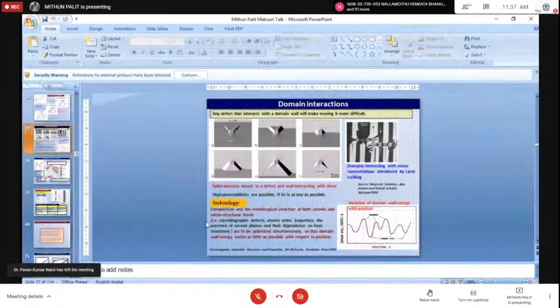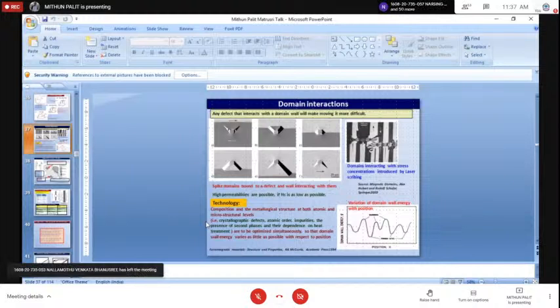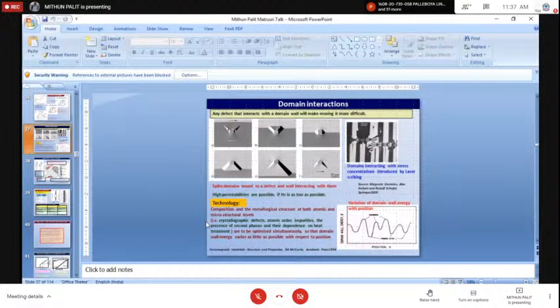So pinning means, for people who are from the material science background, or especially who have studied the mechanical behavior of the material, you may very well know that the dislocations are pinned at different defects, grain boundaries, second phases, and so on. So the same is the case with the magnetic domain wall. Magnetic domain walls also interact with non-magnetic particles, non-magnetic phases, some other magnetic phases, second phases, grain boundaries, or even defects like dislocations and so on. So therefore, when the domain wall boundary interacts with them, the pinning occurs.